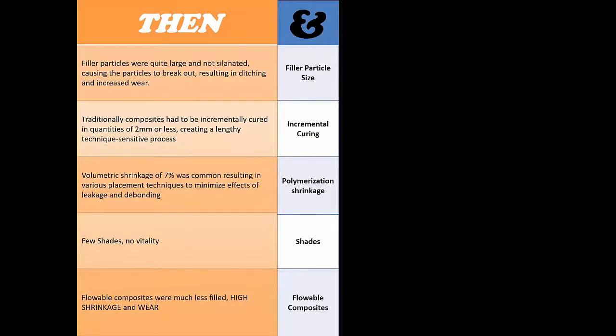In the past, filler particles and sizes were large, they weren't silanated, they tended to pluck out and cause ditching, they had higher wear rates. The curing and incremental layering was limited to 2 millimeters or less, and that made the process more extensive. Even with curing lights, the original halogens took 40-second incremental cures per 2 millimeters. And we've made major leaps with the revolution of LED and fast curing lights, where we can reliably cure, in some cases, I've seen 3, 5, 10, 20-second cures for anywhere from 2 millimeters up to 5 millimeters of thickness. So that's where we used to be.